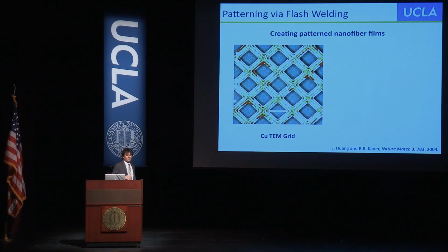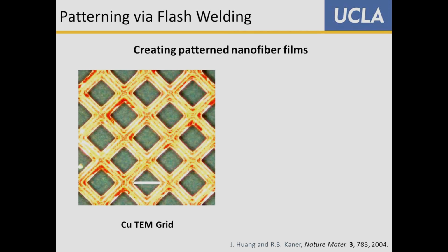And this is a very interesting phenomenon. So it absorbs the light, converts it to heat, and it happens so fast that it melts. You can't melt the polymer by heating it, it simply cross-links. But you can do patterning with this.